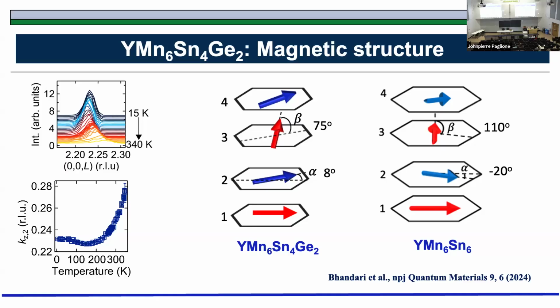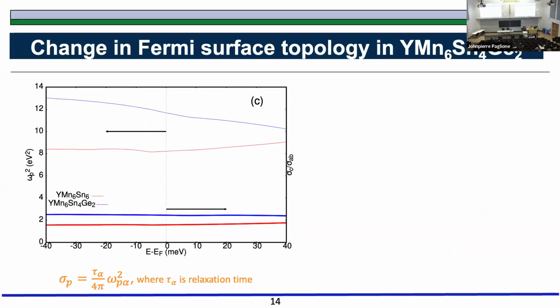And that change in angle was good enough to change its electronic properties. And how did we know that this was changing the electronic properties? That we could calculate, because we measured something interesting in the resistivity. And the resistivity comes from the effect that is happening at the Fermi surface. And we can calculate actually something called plasma frequency. In plasma frequency, it comes just from the Drude model, that the plasma frequency tells you about the anisotropy or isotropy of the Fermi surface, okay? And when we calculate this plasma frequency along Z and in the AB plane, we found that there was a difference between the parent compound and the doped compound.